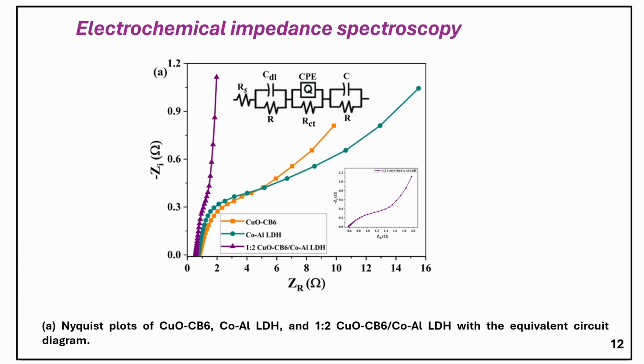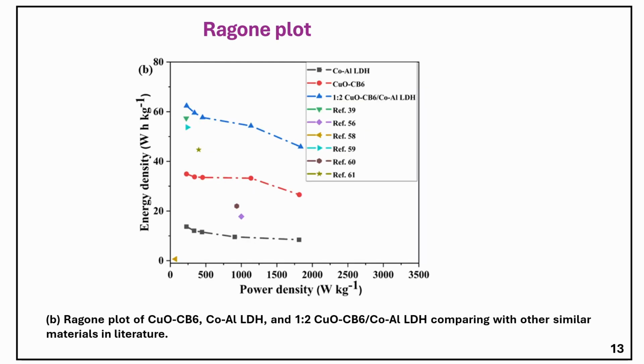Next, coming to electrochemical impedance spectroscopy. This EIS analysis was used to evaluate the resistance of ion diffusion in the 1:2 nanocomposite electrode material. The 1:2 nanocomposite had a lower Rs, that is, solution resistance value of 0.58 ohm compared to the pristine CuO-CB6 and cobalt aluminum LDH, which had values of 0.83 ohm and 0.78 ohm. This lower resistance value in the 1:2 nanocomposite indicated its enhanced electrical conductivity when compared to the pristine materials CuO-CB6 and cobalt aluminum LDH.